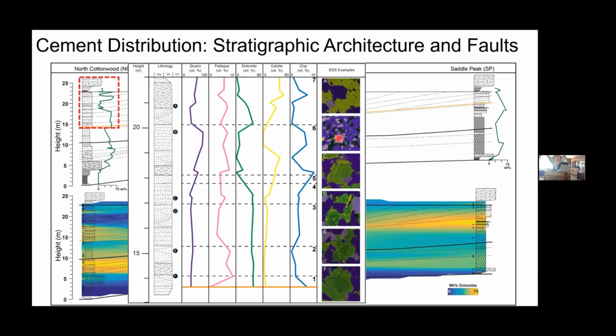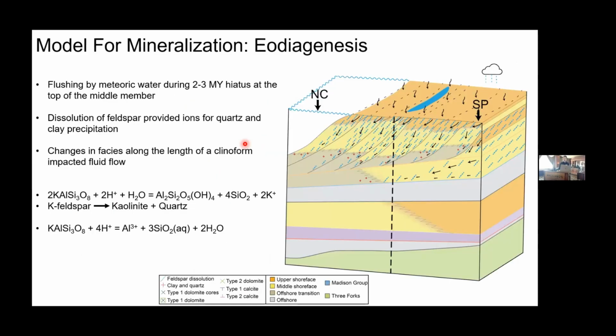So this might suggest that this clinoform itself had a pretty unique fluid flow history relative to the things that are around it. And lastly, getting to the top of the upper siltstone here, this is where the proximity to the upper shale seems to have some control on the morphology of calcite. So I should say upper and lower shale seem to have some type of control on the morphology of calcite, where this type 1 replacive phase is really limited to this uppermost portion of the upper siltstone, and obviously had some type of different depositional or diagenetic history than things around it. So it seems that these clinoforms may have imparted some differences in diagenesis, as they might have restricted fluid flow from one clinoform to another.